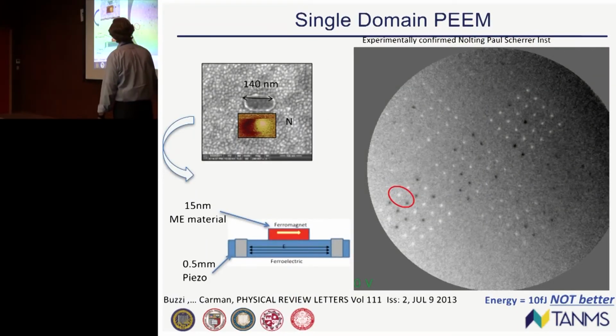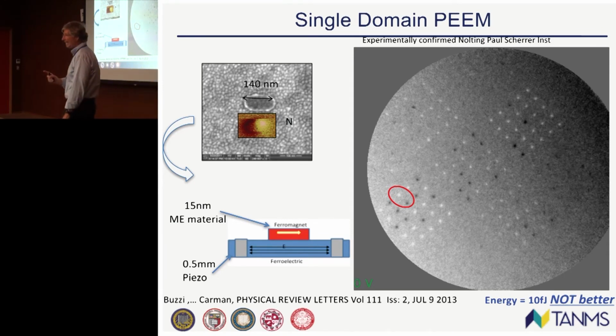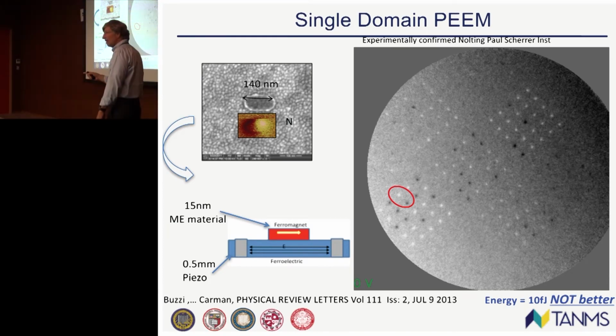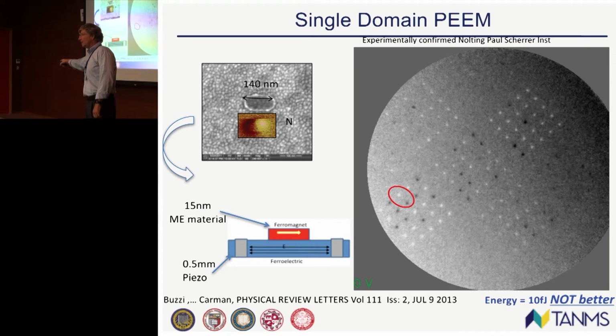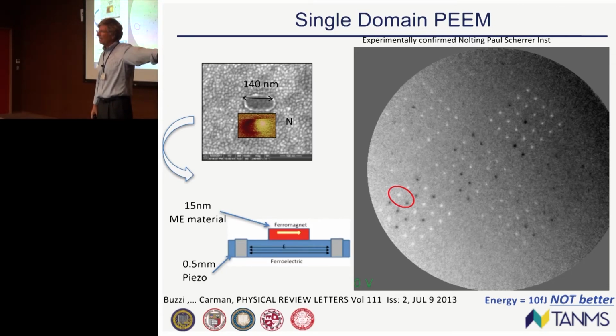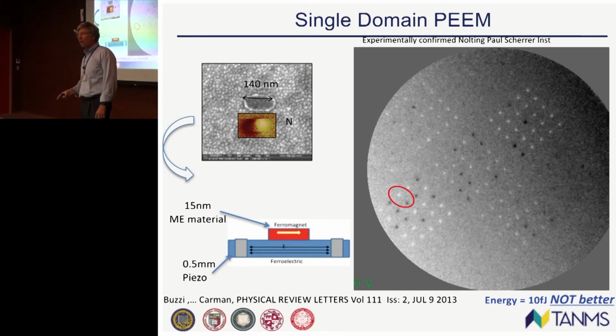So now this is a PMN-PT sample. You see these little dots here? Those are now single domain nickel structures you saw modeled two slides ago. Now I got to tell you again, remember about PEEM? If it's white, that means the X-ray is parallel to the spin state. If it's black, that means it's 180 degrees away. And if it's gray, that means it's 90 degrees. So our goal is to turn that dot from white to gray.